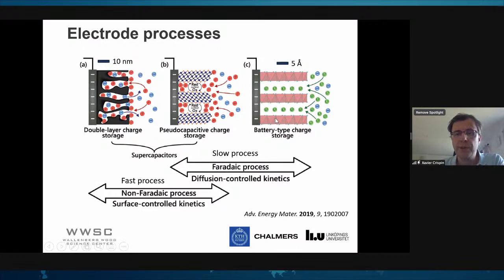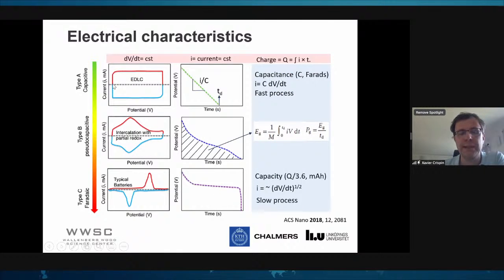So this different behavior will then appear in the electrical characteristic. If you look at a cyclic voltammogram, you scan the potential, you measure the current, and you scan the potential in a constant fashion. So you have a certain scan rate, and you increase the potential step by step, and you just follow and measure the current. What you have in an ideal capacitor, in an electric double layer, is that the current is directly proportional to the scan rate, which is constant in the experiment, times the capacitance. So the value of the current is directly connected to the capacitance value for a certain scan rate. Here you see the level of current, the red, is connected to the capacitance.